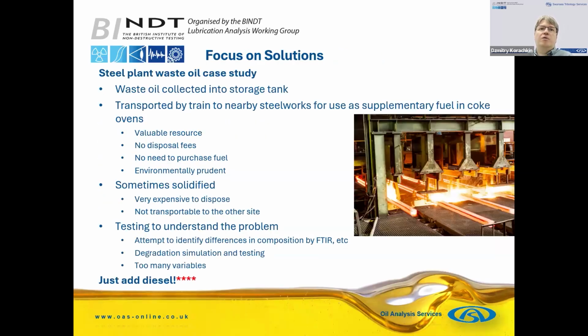And then finally, when a lab is trying to help, they may be able to give you advice not only on what the cause of something is, but sometimes a solution. We have spent some time investigating a situation where some waste oil was turning into a solidified gloop, which could not be used. And then it became very expensive to dispose. Whereas when it stayed liquid, it could actually be used as a supplementary fuel in coke ovens. So we have performed a lot of testing, and we just could not identify what the problem was, whether it was specific contamination, whether it was just a different initial product coming in. There were just too many variables at the time.